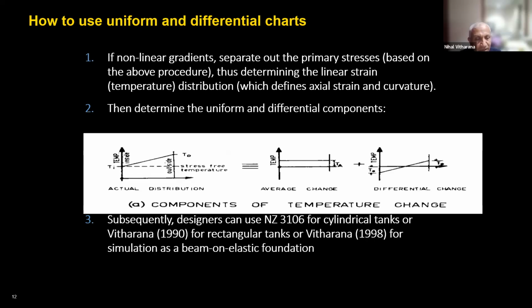So, again, like what you saw earlier on the New Zealand temperature gradients, we got a 0 to 30. So we broke it down to 15 uniform and 15 differential. So those two can be easily used in any of the charts available. Uniform, as I said, if you got a rectangular tank with uniform temperature drop, you get very high axial forces. That's why most rectangular tanks, if not properly designed, tend to crack vertically along the length.